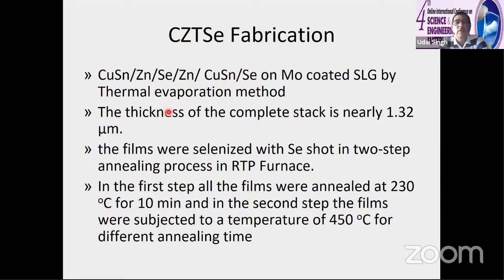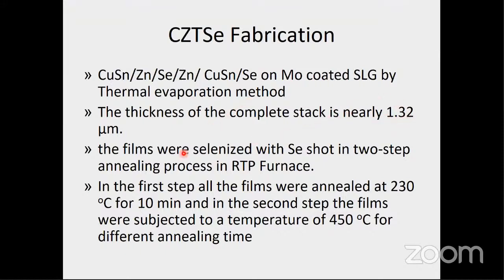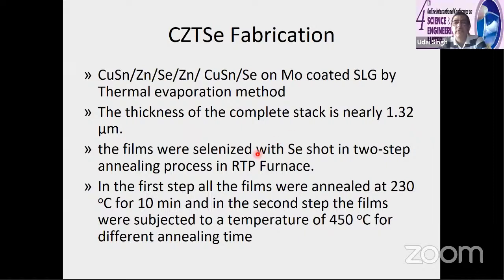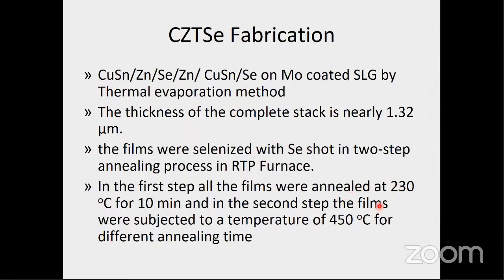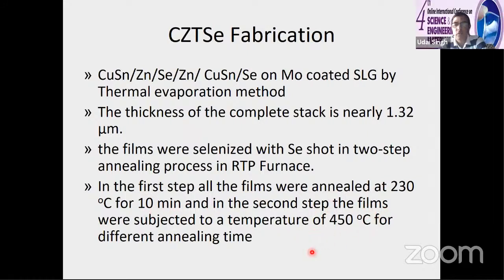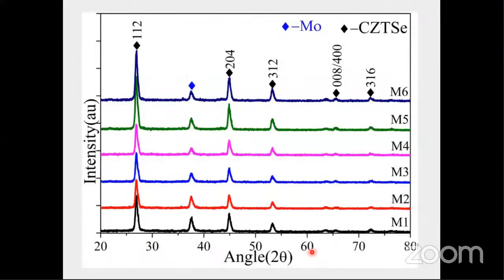This we have got by optimizing different layers. The thickness is around 1.32 micron, and then they were selenized with selenium at different temperatures. We have used two-step annealing, 230 degrees C for 10 minutes, and in the second step we have gone to around 450 degrees C. So this is XRD.